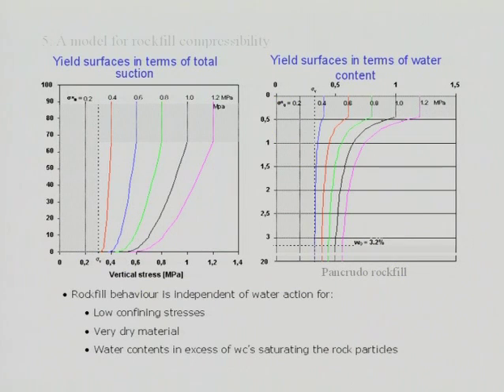Now, the actual yield curves for the rockfill that we were testing look a little bit like that. The graph on the left refers to suction as a measure of the water energy. The graph on the right to water content. This is isotropic conditions, and here are a number of those yield curves, and you may see this gray shadow here, and those indicate the places in which there is no influence of water content, for two reasons, essentially. If the material is very dry, we shouldn't have any yield.